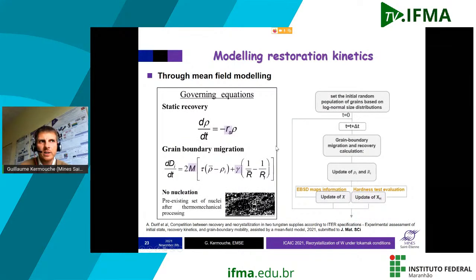So here are basically the equations that we have to use to model recrystallization and recovery. The first equation is the decrease of the dislocation density with time. Okay, so here it's the dislocation density, and this is the recovery parameters. And the second equation is the movement of the grain boundary. So the increase of the grain size depends on the stored energy that is here, and depends also on the grain radius. And here you can see this parameter, that is the grain boundary mobility. Then we can work on the full microstructure.